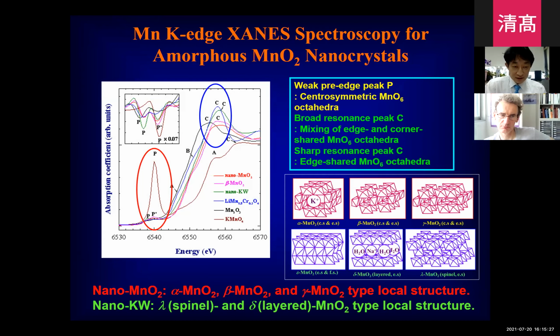From the pre-edge peak, nano MnO2 is the red line, and the green line represents the spectrum for nano KW. Both materials show very low intensity for pre-edges. So this is the evidence for the stabilization of manganese ion in the octahedral symmetry. We were focused on the variation of the resonance peak, peak C. It is well known from the reference data that the intensity and the sharpness of this peak is proportional to the relative concentration of the edge sharing and the corner sharing of the MnO6 octahedra. In the case of a purely edge-shared structure, we can observe a very strong and sharp peak like the KW. But if the manganese oxide lattice possesses edge sharing and corner sharing, we normally observe a much broader and lower intensity peak C. So this is the case for the nano MnO2.